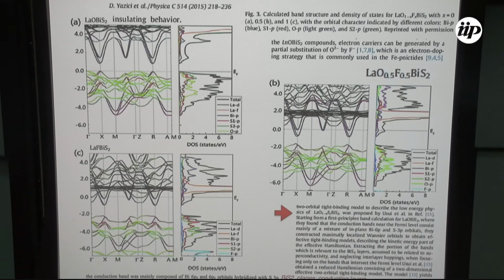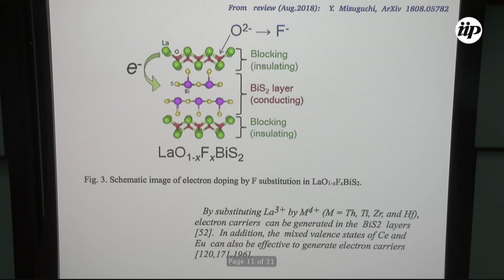And here you see the density of states, and you see the character of the bands. Character of all the bands which you are seeing here. In principle, one can see that the main bands near the Fermi level are related to bismuth p orbitals and sulfur p orbitals. And so, of course, there has been some kind of a downfolding approach.